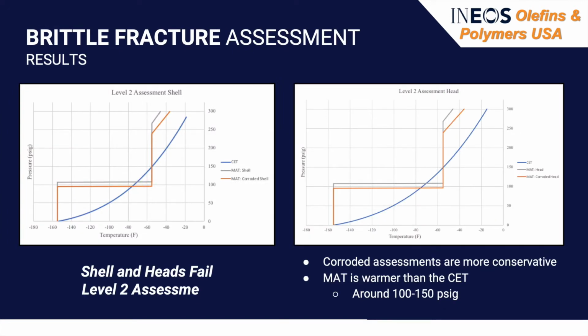In the spring semester, a brittle fracture assessment at DD308 was conducted via industry codes ASME B31.3 and API 579. Both the shell and the head of the pressure vessel were tested, as these were the weakest components. The gray line is the MAT, minimum allowable temperature, uncorroded, and the orange line is the MAT, corroded. The blue line is CET, the critical exposure temperature. At any given pressure, the MAT must always be colder than the CET. As can be seen, from roughly 150 psi to 100 psi, the MAT is warmer than the CET. Thus, the pressure vessel failed the assessment and the team moved forward with designing a solution.